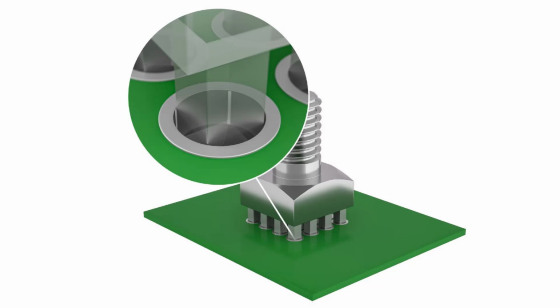Due to their high heat absorption, press-fitting of the REDCUBE press-fit should be carried out last, and this is after all soldering processes are completed. Resoldering REDCUBE press-fit terminals after the press-fit process is also not recommended. Resoldering can potentially lead to partial destruction of the cold weld and delamination of the circuit board. This could result in the permanent loss of mechanical stability in the press-fit zone.